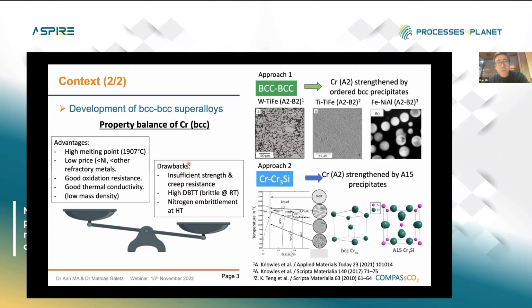So to strengthen chromium, in our project, we use some intermetallic precipitates to achieve this goal. And to strengthen it, we have used 2 approaches. The first approach we use is to strengthen it with a coherent BCC ordered intermetallic phase from the BCC prime microstructure, mirroring the gamma prime microstructure in the nickel-based superalloy for high temperature application.